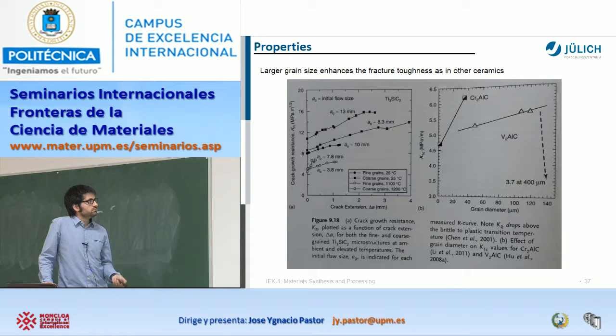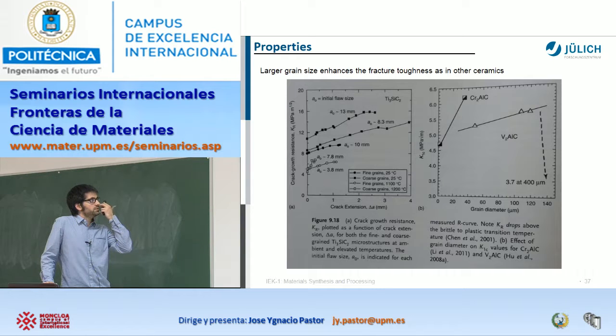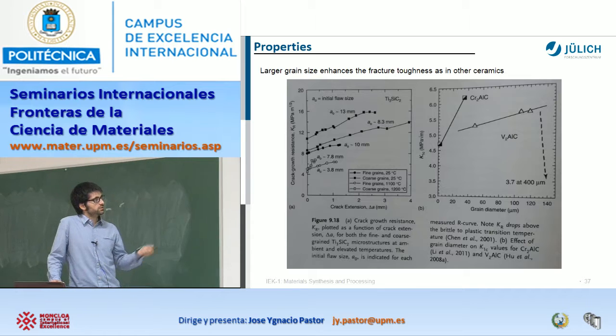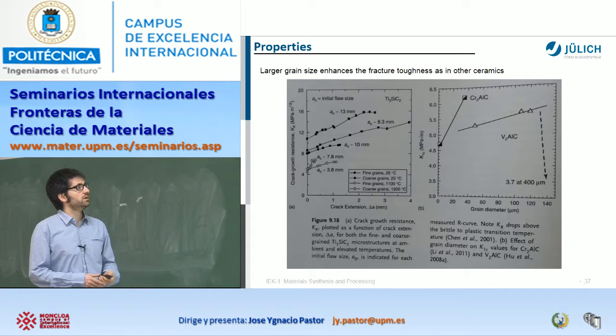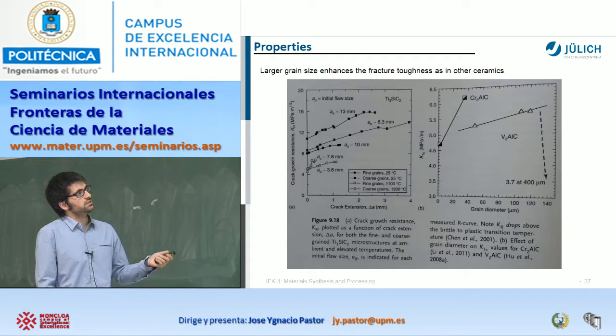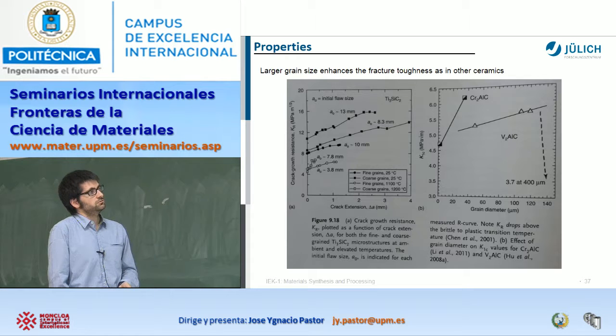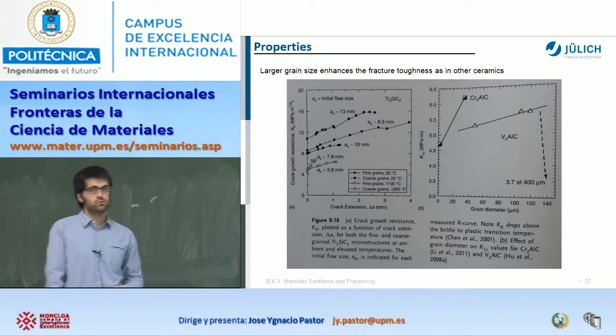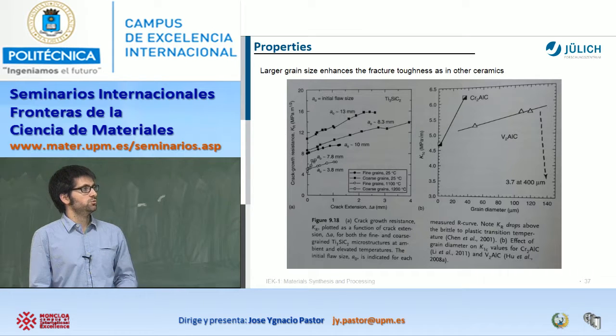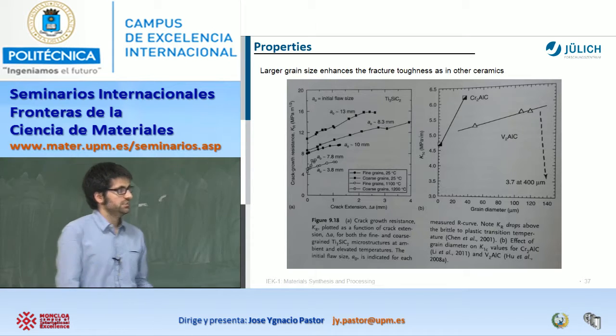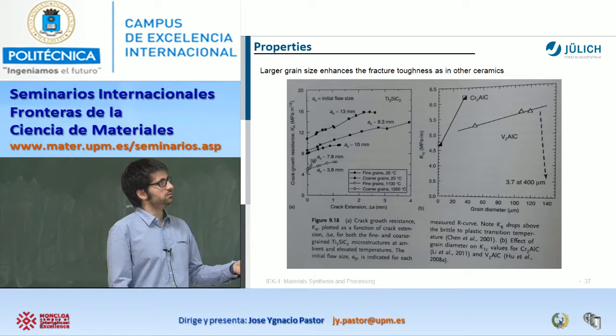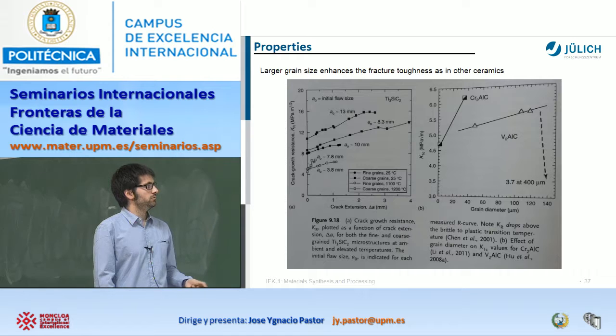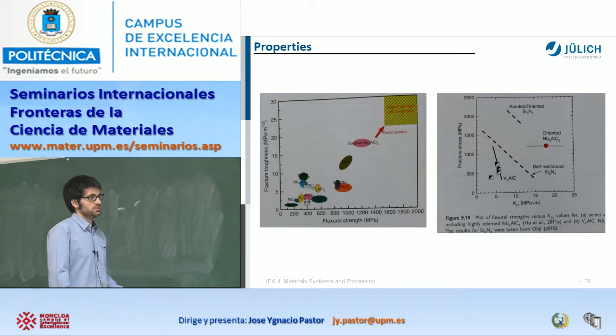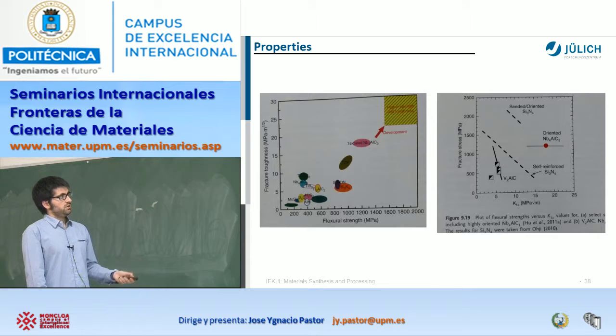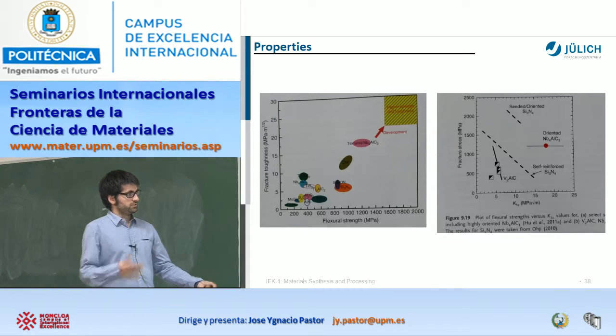Okay, and again, we mentioned before that it's better for the flexural strength to have small grain sizes, but for fracture toughness, of course, you need these kink bands, and they are promoted with larger grain size, and here they improve the fracture toughness, like in other ceramics. If you have larger grains, obviously your fracture toughness will be higher. Okay, and here there are a few examples about that, but as you see, we are talking about really resistant materials.